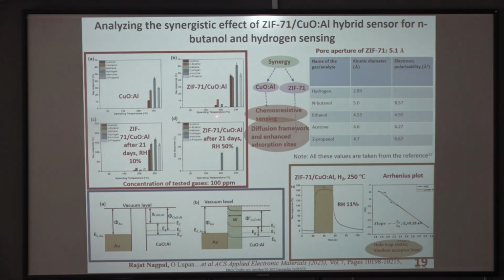Now, what is the reason behind high selectivity for n-butanol and hydrogen? That we will try to understand through this table. Here we can see, due to the small kinetic diameter of hydrogen compared to the pore aperture of ZIF-71, it can easily diffuse through the framework, which due to the molecular sieving effect, gives high sensing response for hydrogen. But comparing among VOCs, here we can see they have comparable kinetic diameter compared to the pore aperture of ZIF-71.